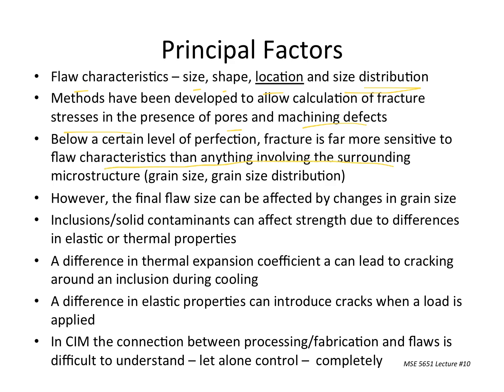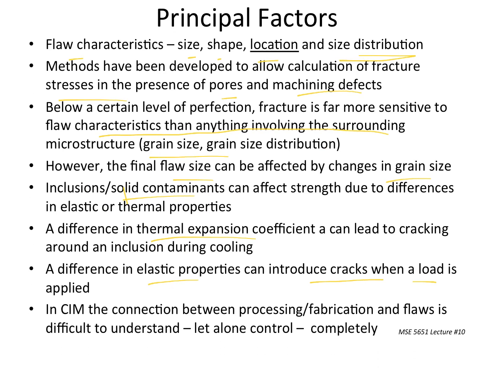Fracture is far more sensitive to flaw characteristics than anything involving the surrounding microstructure. Final flaw size can be affected by changes in grain size. Solid contaminants can affect the strength. Differences in thermal expansion coefficients between one phase and another in a ceramic can cause cracking. Differences in elastic properties can introduce cracks when a load is applied. We've seen the consequences of that. Whoops. And the ceramic injection molding connection between processing, fabrication, and flaws is difficult to understand, let alone control completely. So I hope you have the impression that this is a complicated process, densifying these things.